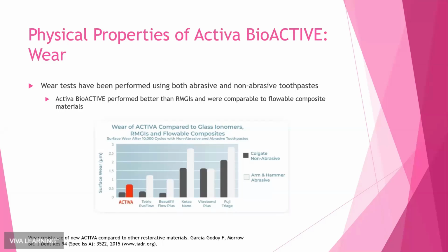So on the left side of the bar graph, we have the non-abrasive toothpaste, and then on the right side, we have the abrasive. And you can see that Activa performed incredibly well in comparison to the other materials. So it showed the least amount of wear for the non-abrasive and the least amount of wear for the abrasive toothpaste. So again, when we're considering restorative materials in a high activity part of the mouth, this is looking like it would be really promising.